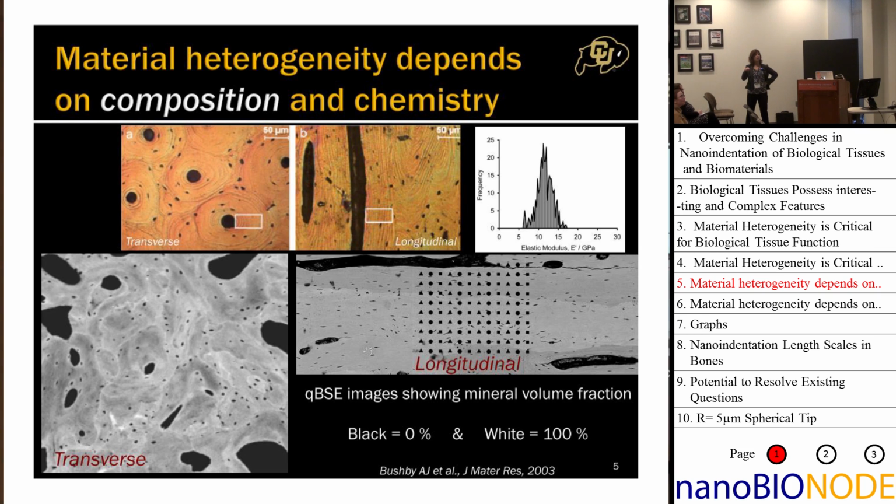So you can see bone adjacent to these canals is more newly formed, it's younger, has less mineral. The existing bone here in these interstitial spaces has more mineral because it's been around for longer. It's a thermodynamically driven process over time. We'd expect that to happen. And it turns out that we do see correlations that I'll show you in a minute.